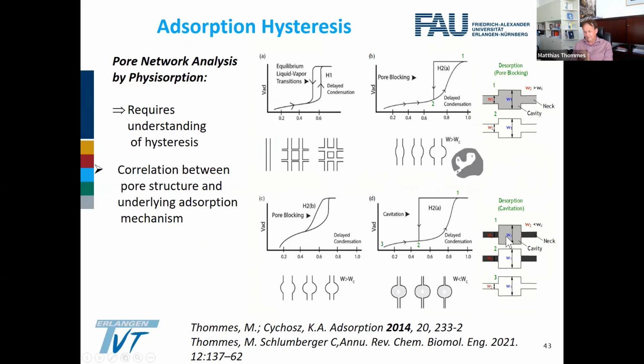This pressure is larger than the pressure needed to empty the neck. So you can have a situation where you empty the cavity, but the neck still remains completely filled. And then you empty the neck at a much smaller pressure, which is again correlated quantitatively with the size of the neck.